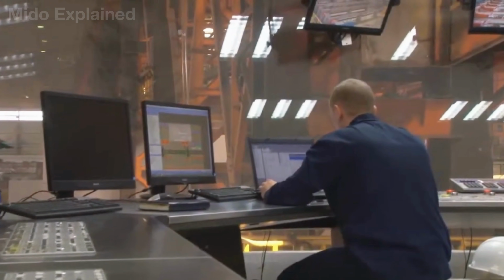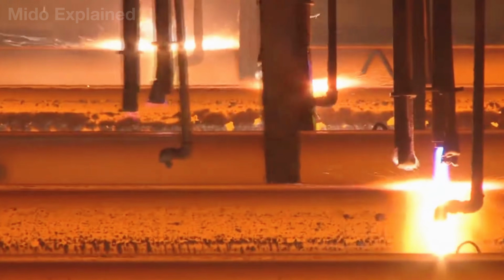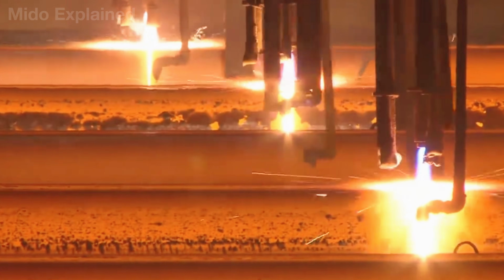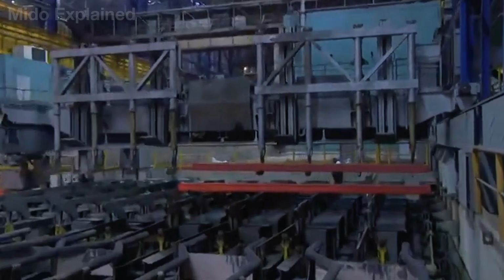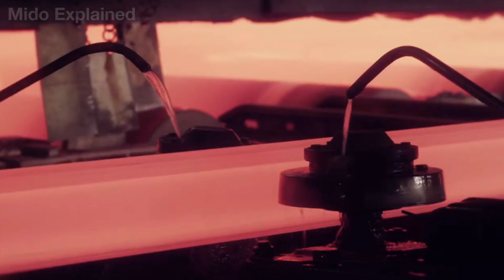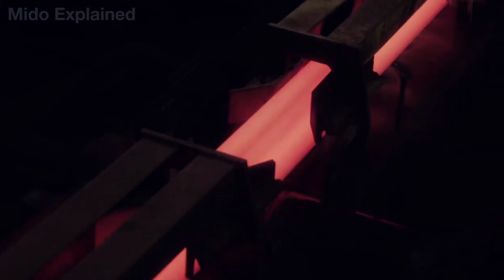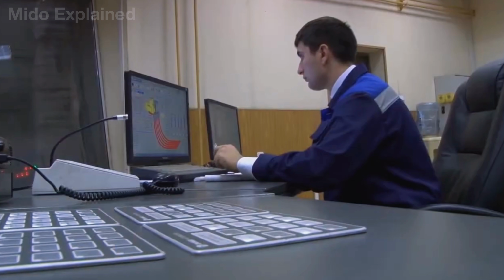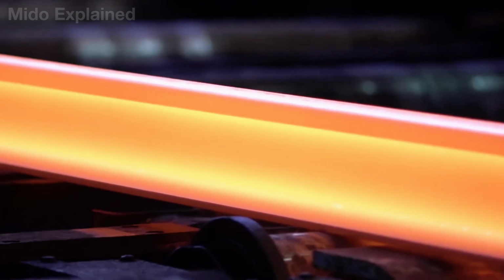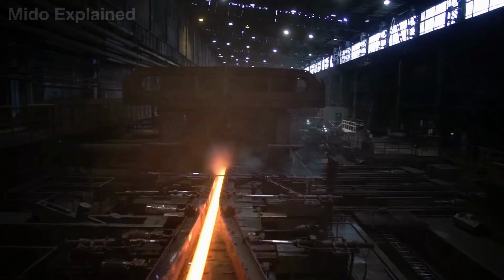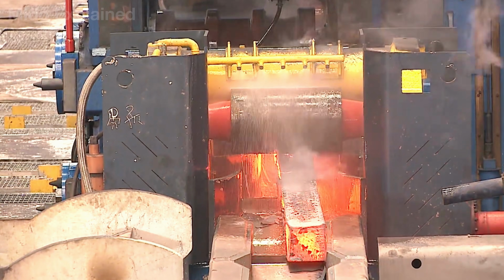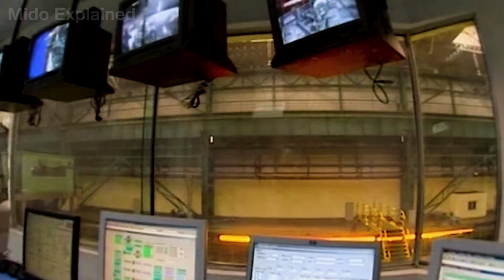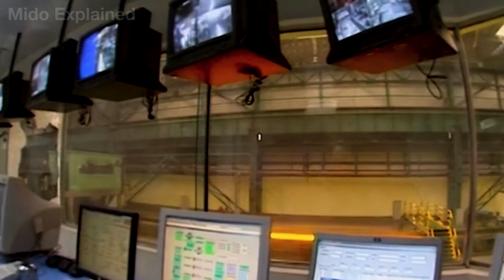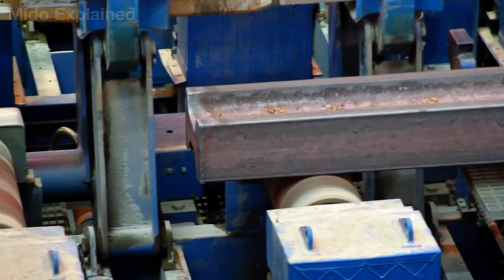After being formed, the rails remain at very high temperatures and contain significant internal stresses within the metal. To stabilize the structure, they are passed through a cooling system hundreds of feet long. High-pressure nozzles continuously spray the surface with water or a fine mist, lowering the temperature to around 200 to 300 degrees Fahrenheit. If cooling is too rapid or uneven, the rails can warp or develop small cracks.